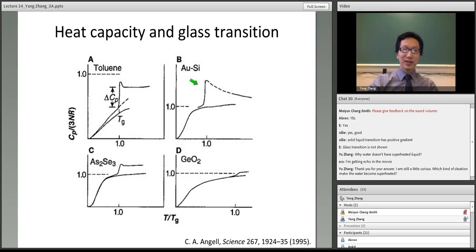If the specific heat shows a discontinuous change, then this would indicate a first-order phase transition. But the so-called glass transition itself is not a first-order phase transition. You can see the specific heat still changes continuously, but definitely there is something going on. It looks like a second order, and some theories try to explain the glass transition as a second-order phase transition. But still, most people believe that the glass transition is not a true thermodynamic phase transition, but rather